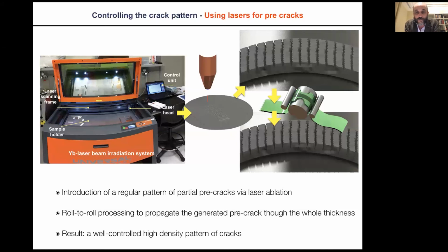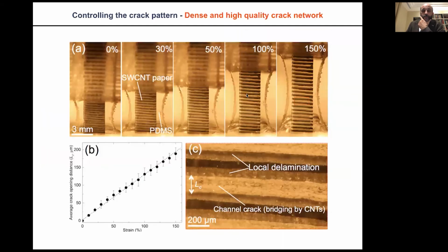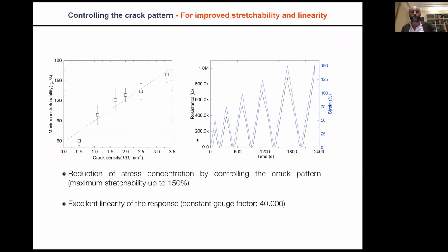If you go to the second generation of sensors, what we do is to control exactly the distribution of the cracks in the sensors by using a specific laser pretreatment, by introducing pre-notches, I mean, pre-cracks that are going to control where the cracks are going to happen. By activating this, you get sensors that are much more organized in terms of crack morphology. You get a very good linearity with a gauge factor of around 40,000, so a huge gauge factor, and a stretchability that increases with the number of cracks up to 150%. The message I want to give here is that by using ideas and technologies that come more from the composite world, I think we have a big role to play in flexible electronics and the improvement of microstructures used as functional sensing structures for flexible electronics.